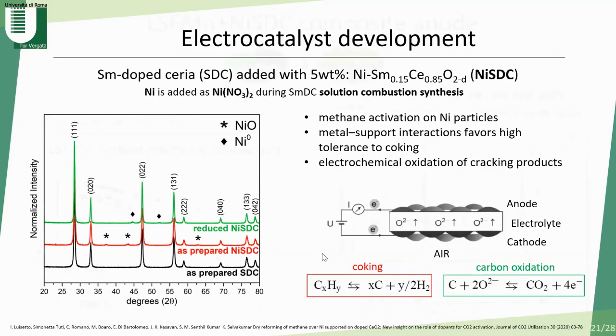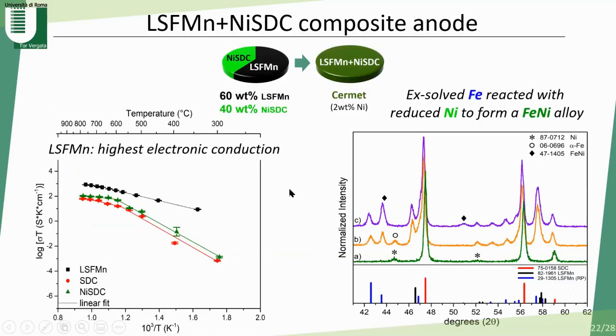And okay, so we designed our innovative composite anode by mixing the perovskite oxide at 60%, which shows a better electrical conductivity than nickel SDC, with the good electrocatalyst. The overall amount of nickel in our composite anodes is about 2%, which is much lower than the about 50% of the conventional nickel YSZ anodes.